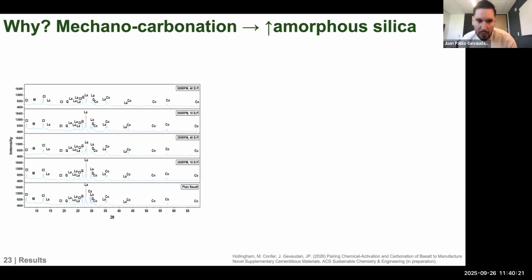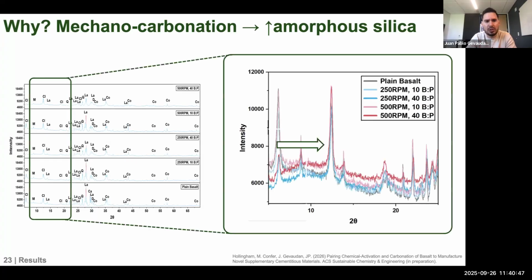But one thing that we're really interested in is always understanding the why. We always ask a million why questions when we see our results. And here we're looking at XRD data. We're really interested to understand why mechano-carbonation is increasing that reactivity. And we believe it's because we may be actually increasing the amount of amorphous silica. So in order to look at that, we are very interested in looking at the amorphous hump in XRD results.